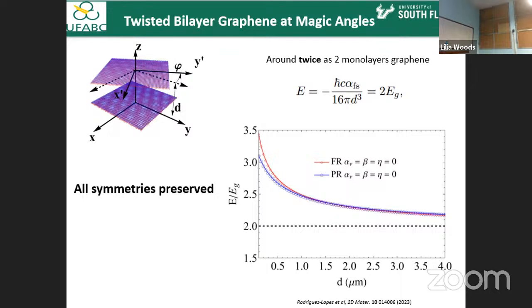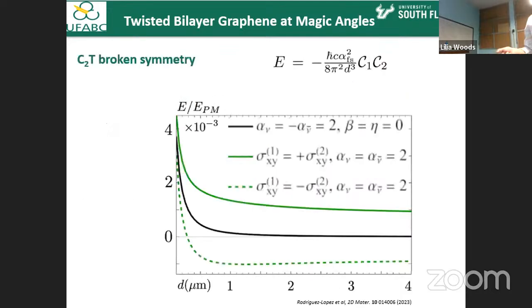Two times graphene layers. And then the most interesting case is when the time reversal symmetry is broken, which we can control via some parameters here. And we covered this case when the time symmetry is broken. Bilayer graphene, magic